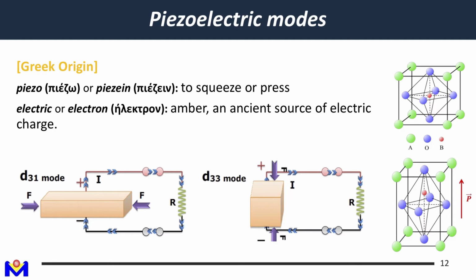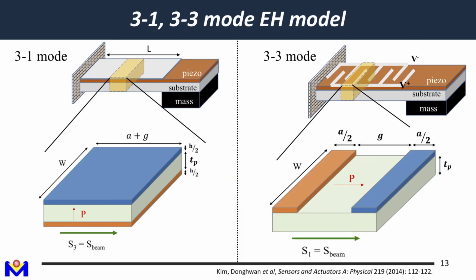One in 3 direction, one in 1 direction. And the other choice is if we have the electric field that's in parallel with the force field, we call it a 3-3 mode. So with D31 mode and D33 mode, we actually have different piezoelectric constants, D31 and D33. And for typical PZT ceramic piezoelectric material, D33 is about 1.5 to 2 times larger than D31. So a lot of people are talking about D33 transducer could be a better choice because of the larger